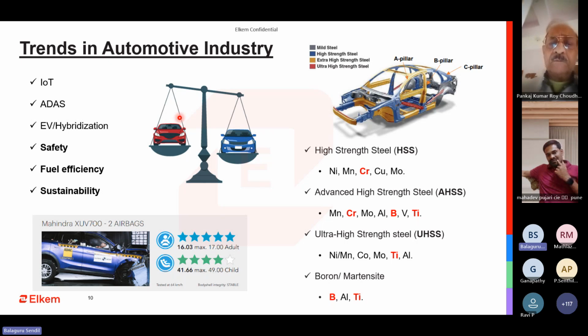We were expecting this transition to happen very slowly, but because of the third factor, sustainability, and our scrappage policy of cars, this is actually driving these two factors to be adopted very fast. So the impact on the foundry will be much faster. We are not so sure exactly when we are going to realize this impact, but some foundries, especially the bigger ones, have already started to feel it. They are more concerned about the trace elements like boron and titanium, which is causing a problem since they are using a lot of their own company scrap, and also a lot of scrap that they buy for sustainability purposes, recyclable scrap, off grade scraps.